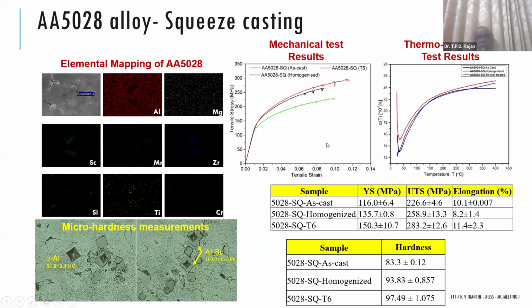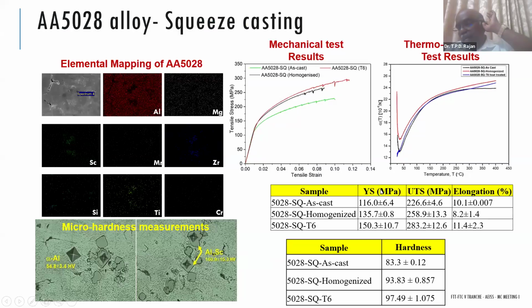And again, these are the studies on the squeeze casting, that is gravity and squeeze cast. So squeeze casting means normally we apply the pressure, and here we can see that as cast has 116 yield strength and 226 ultimate tensile strength. But when we homogenize and do the T6 heat treatment, it enhances to 283 megapascal. So heat treatment also has a major role in enhancing the properties. So these particular alloys are being made, and we have now transferred it to an Indian industry for rolled sheets.